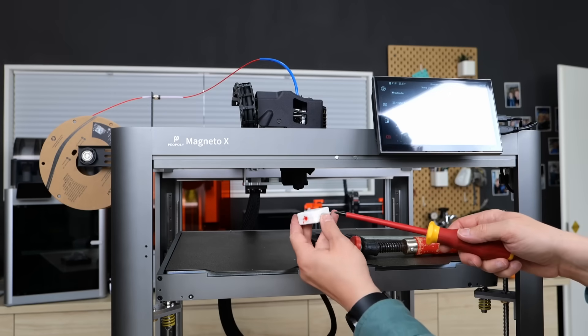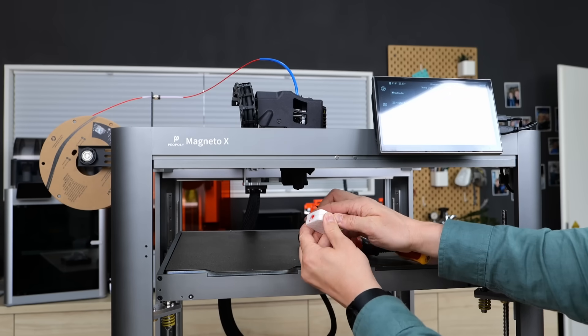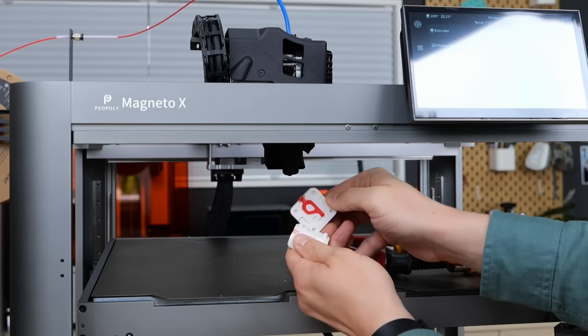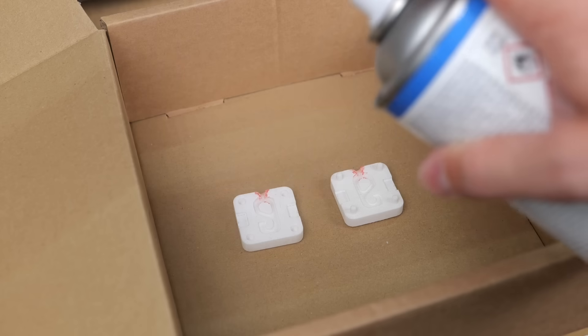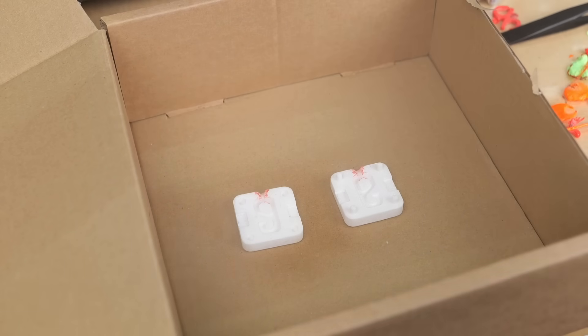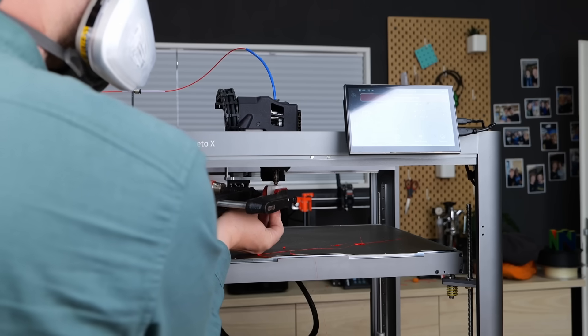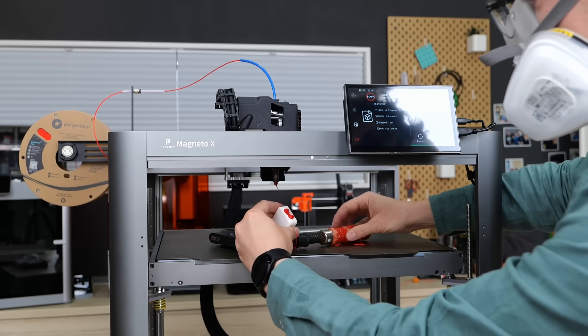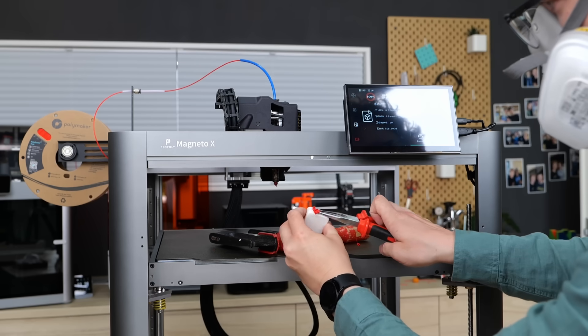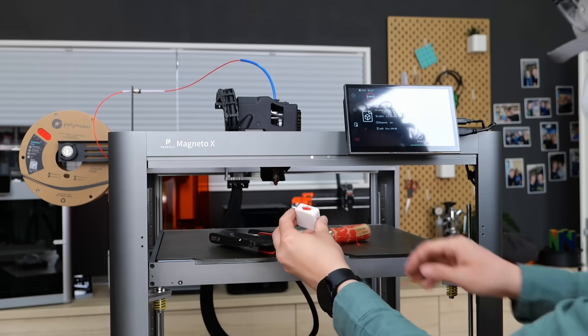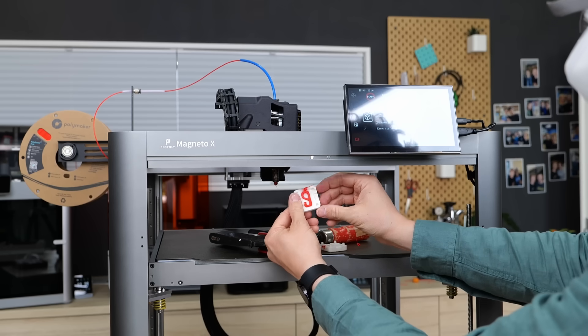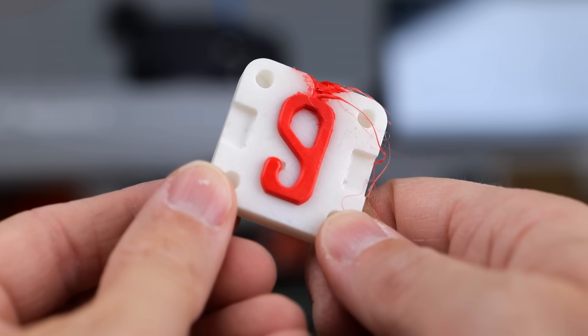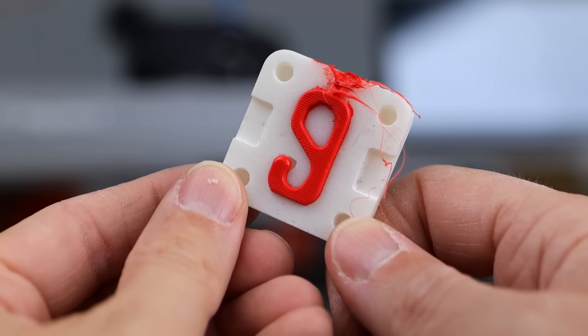I already noticed, because of the hard time that I had to open the mold, that the first shot wasn't that bad. Still, I was a bit upset that I didn't get that much further than on the Prusa. To fix the sticking issue, I also sprayed the halves with some mold release and continued adjusting the parameters and after a bit of tweaking of the temperatures and the injection speed, I got this. Not 100% perfect but almost and honestly quite a success because I didn't even preheat the mold.